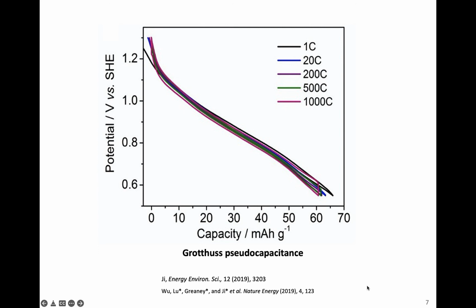Note that this is a test to approach the theoretical rate behavior of a battery electrode material, where the electrode mass is small. Currently, charging a practical battery device in 3.6 seconds is still very challenging due to the engineering limits, for example, joule heating of the device at a high current. The redox reaction here is so fast that I referred to this reaction as Grotthuss pseudocapacitance.